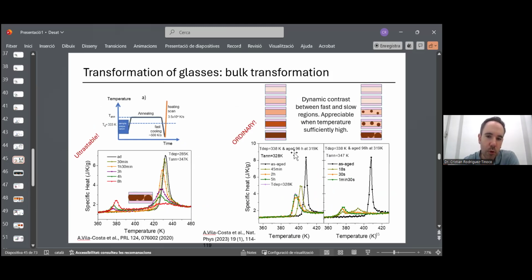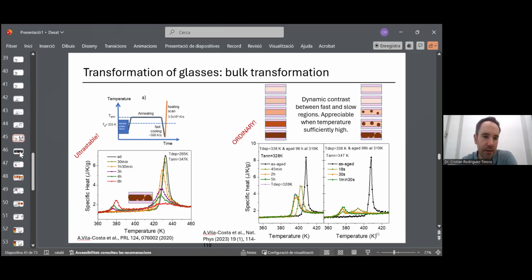This is important. We observed something similar also in the ordinary glass. Okay, if we age the ordinary glass, if we prepare a glass by cooling from the liquid and we age the glass to increase the stability a little bit, depending on the annealing temperature, we can see either only this change in the glass before observing the liquid, or if the temperature is larger, we can see the emergence of these liquid regions. Okay, so depending on the annealing temperature, we see one process of equilibration into the final state, or another mechanism. Okay, again, not many details about that, but this is also an interesting observation.